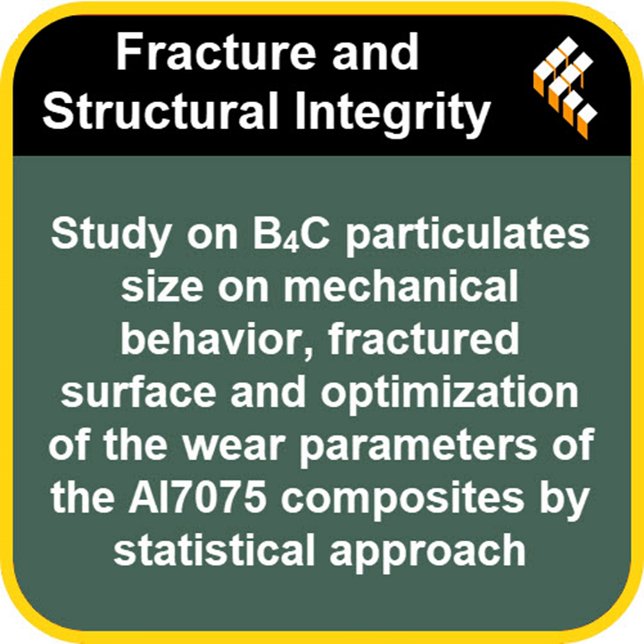Like a weak point magnifier? Sort of, yeah. Second, statistically, a larger particle has a higher chance of containing an internal flaw or imperfection that's big enough to cause problems, a critical size flaw. So they're just more likely to fracture internally under load. And once those reinforcing particles break, they're no longer reinforcing, they become defects, weak points. That leads to a faster decline in the composite's overall strength. So even if they seem strong initially, those bigger particles can actually become the Achilles heel under serious stress.